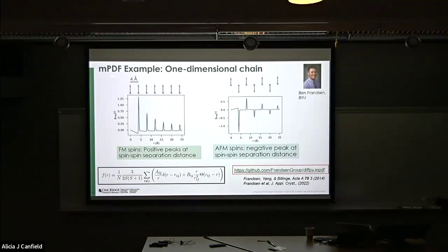So this is an example that I hope nicely shows how the technique works. So here, if you consider a one-dimensional chain, this is a ferromagnetic chain with spins, atoms separated by 4 angstroms. If you look at your MPDF pattern, you have a positive peak at 4 angstrom, and then another positive peak at 8 angstrom. So ferromagnetic spins give positive peaks. And if you look at your antiferromagnetic spin chain, the first nearest neighbor spin-spin interaction is antiferromagnetic. This gives you a negative peak in your PDF pattern. The next nearest neighbor is ferromagnetic. This gives you a positive peak, and so forth. And you can see how you can first just visualize your magnetic structure using this MPDF, and then you can start to fit the data.